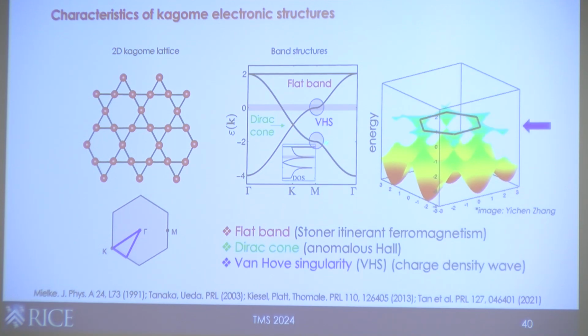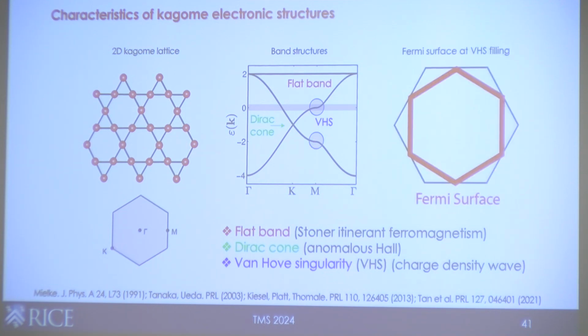And the third one is this pair of magical Van Hove singularities that will give you a divergent density of states in 2D. And then when you tune your chemical potential to be there, you get this idealized Fermi surface that has 3 pairs of parallel sheets that would give you a nesting condition. And from this, one would expect to see a charge order that, in the in-plane direction, has 2 by 2. So these are the 3 key predictions associated with a Kagome lattice.